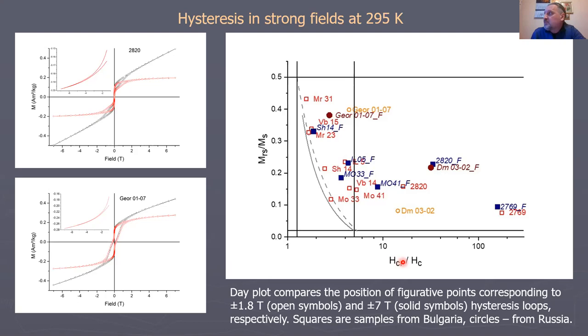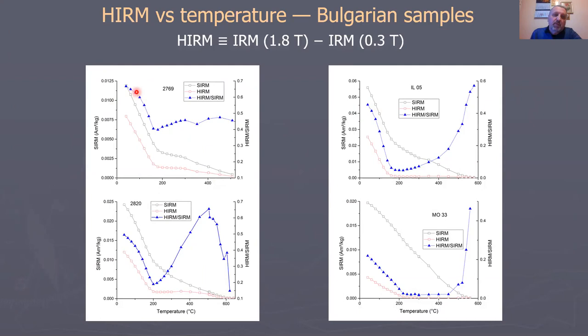So now, a more advanced experiment, magnetization versus temperature. Here I plot SIRM and HIRM, which is simply the hard part of IRM acquired above 300 millitesla, in black and red, respectively, and in blue, the blue triangles are the ratio.